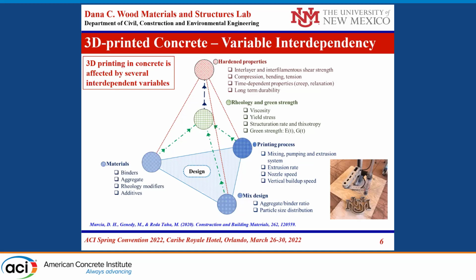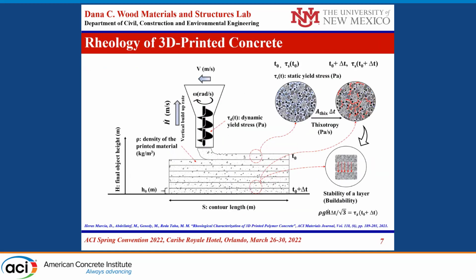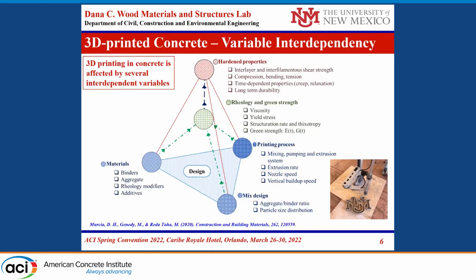Because if these, and some of the discussion today was about the overlap, trying to improve these properties to make sure that we're not going to have interfilamentous failures. Then the compressive strength, bending strength, time-dependent properties, and long-term durability, which still has a long way to be looked at because we do not have a lot of these materials tested in full scale yet. But interesting, before I leave this, is that the printing process is a key effect on the material properties that is different than what we used to do with typical concrete.